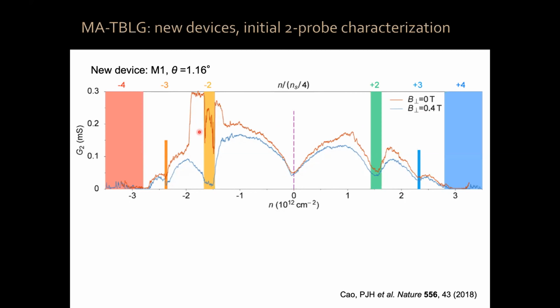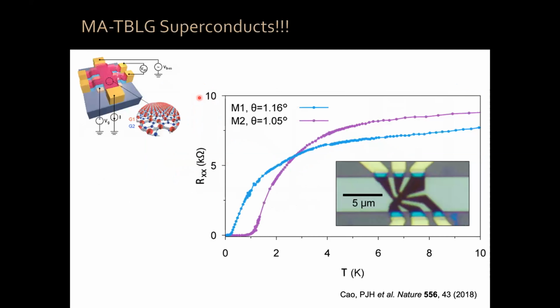Okay. Well, now we change to our 4-terminal geometry measurements so that we can measure exactly how well this wants to conduct. And to our surprise, what we saw is that magic angle twisted bilayer graphene superconducts. Okay, if you measure the resistivity or the resistance as a function of temperature, you have this drop, by several orders of magnitude, below our noise measurement floor. These are data for 2 samples. We have by now measured many samples. Okay, and magic angle graphene is a 2-dimensional superconductor.